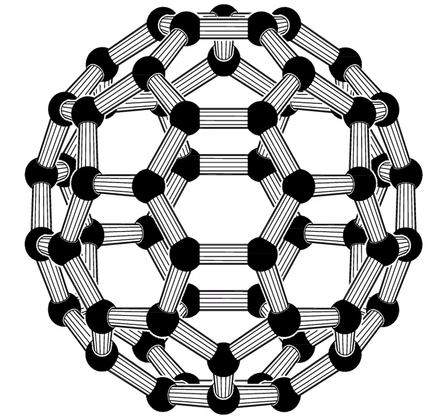In the parchment model, a single sheet of graphite is rolled in around itself, resembling a scroll of parchment or a rolled newspaper. The interlayer distance in multi-walled nanotubes is close to the distance between graphene layers in graphite, approximately 3.4 Å. The Russian doll structure is observed more commonly. Its individual shells can be described as SWNTs, which can be metallic or semiconducting. Because of statistical probability and restrictions on the relative diameters of the individual tubes, one of the shells, and thus the whole MWNT, is usually a zero-gap metal.